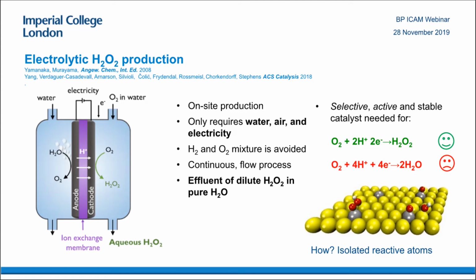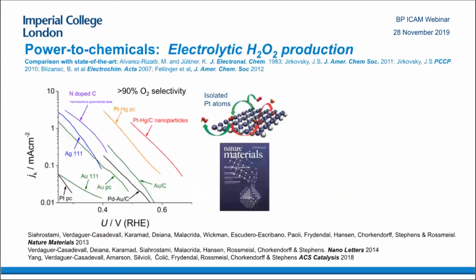So we had the idea, why not try using mercury instead to isolate the platinum atoms? So we tested that out. It's actually very easy. You simply electrodeposit mercury onto platinum, and we tested it. We found that the activity was orders of magnitude better than the prior state of the art. We thought this is really great. Let's try and commercialize it.